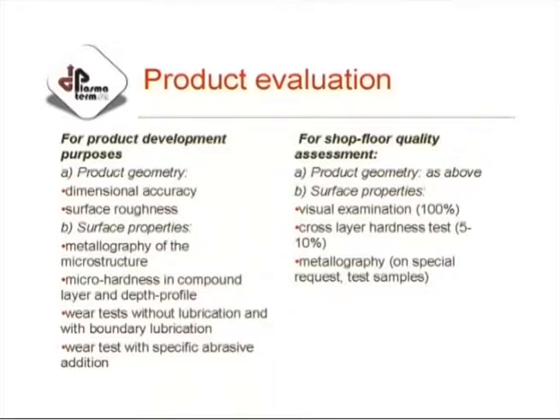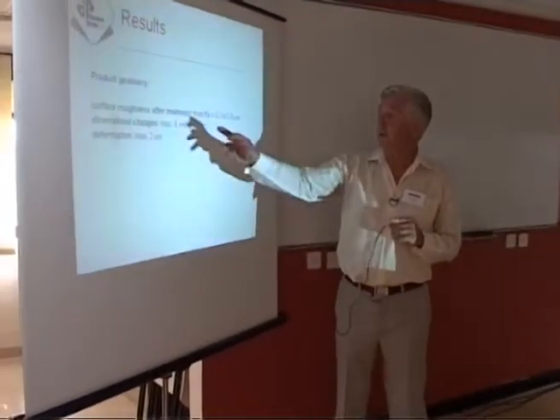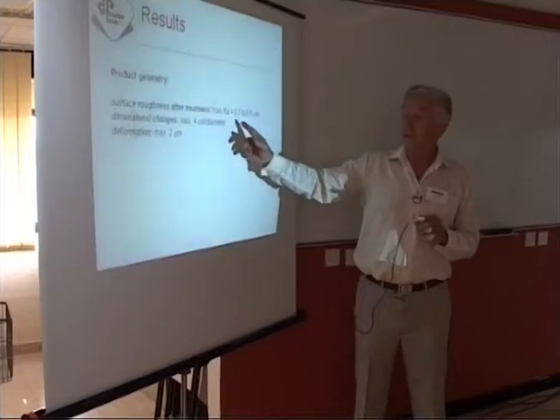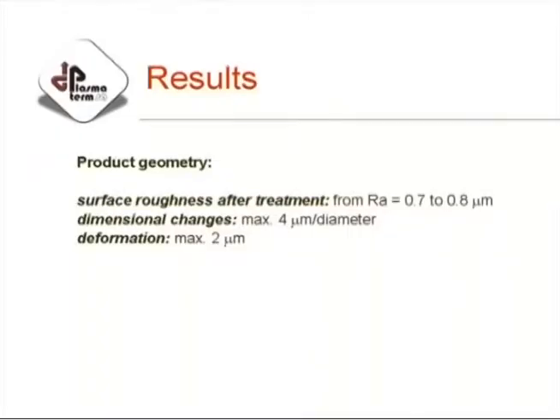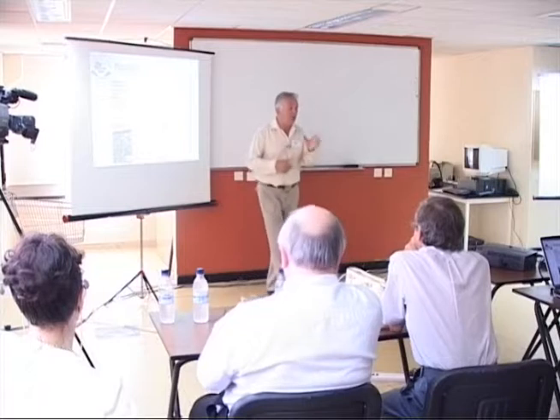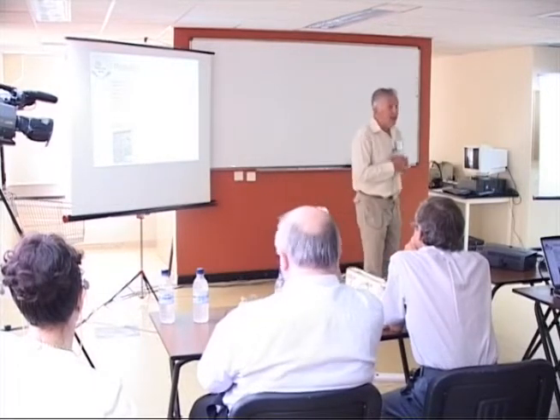We certainly will control the product geometry and the surface properties like visual examination, cross-layer hardness test, and metallographic examination when that's requested on some samples. Typically, the product geometry considers dimensional changes up to maximum 4 microns in diameter. And this is a rather good value. The deformations inside of this tolerance field were about 2 microns, so a really very, very good result. And the surface roughness around 0.8 microns Ra.